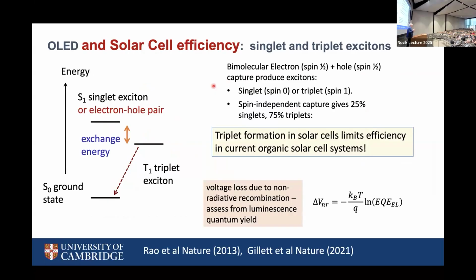The ideal solar cell, if you choose not to wire it up, should look particularly fluorescent. Photons absorbed produce electrons and holes, which can't escape because we haven't turned the device on, so they should recombine, produce photons out. We don't expect to see that because we don't see that with silicon. And first of all, it's not very luminescent, and secondly, it's flat. So we haven't been sort of tuned to think about a solar material as being luminescent, but we definitely see that with perovskites, and we're starting to see that with the organics.